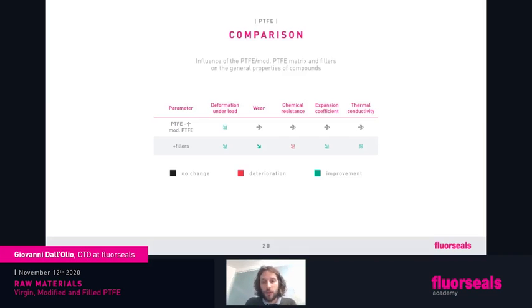Also, the expansion coefficient, and this is a very important thing we didn't mention before. The expansion coefficient is another weak point of PTFE. PTFE, due to temperature changes, moves a lot. So many applications that go up to very high temperature and then go down don't like to have seals that move due to thermal expansion. So adding a filler will reduce the thermal expansion, and that's really good for engineers that have to think about the seal's behavior at low but also at high temperature.